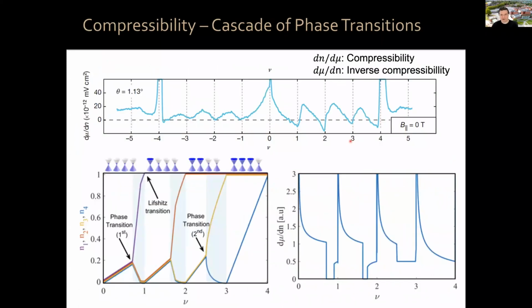Okay, I had here a zoom in on these regions. This is again the inverse compressibility. You should think of the compressibility as like the density of states, so inverse compressibility is inverse density of states. What you can see here is that if you start from charge neutrality, you have your 4 flavors, spin up, spin down, valley K and K prime. You start filling them all at the same time.